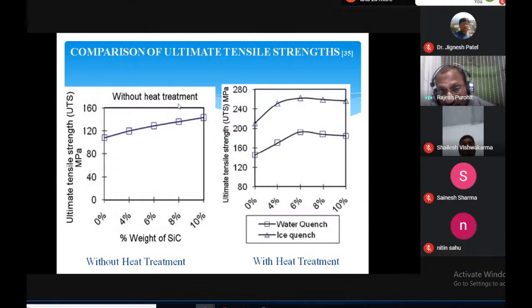The right graph is showing the results after heat treatment. In this right graph, the bottom curve is for water quench, and the upper curve is for ice quenching. With ice quenching the rate of cooling is very high, so because of that we get better properties, higher ultimate tensile strength, using ice quenching. With water quenching we have got quite lesser UTS, and it is maximum at about 6 weight percent of the SiC, after which it is slightly decreasing. Okay.